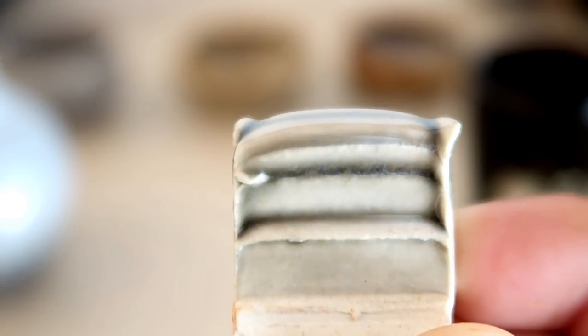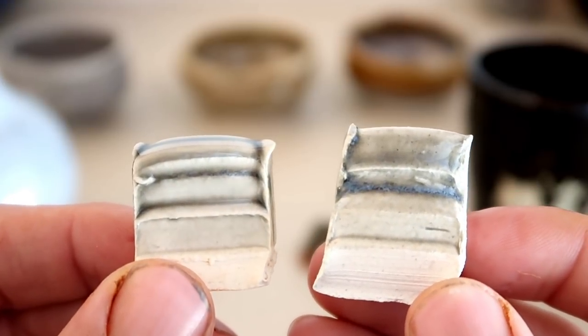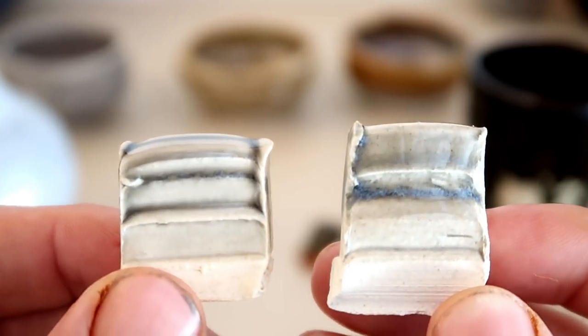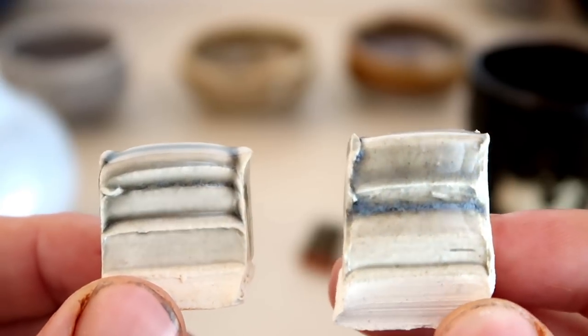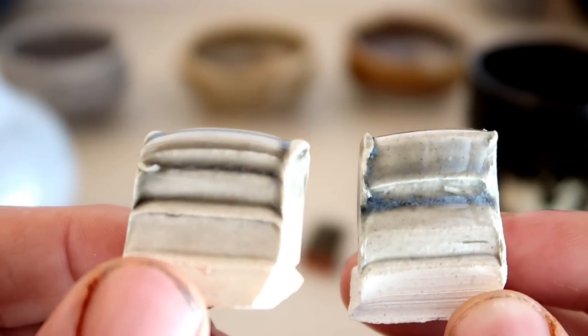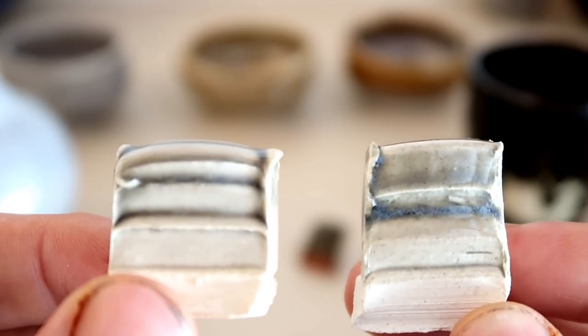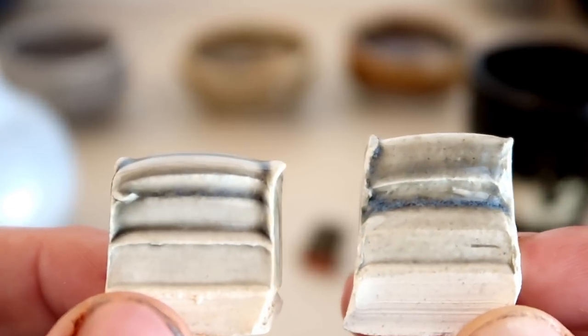This of course is on a porcelain clay body and this one looks a lot better than the B-Mix. I understand now why people mainly use this for porcelain. If we put the two side by side you can really see it — this one looks a lot more blue than this one. I wanted a gray, I didn't want a light blue. So on B-Mix it comes out this strange light blue, although it is a good glaze. I'll keep it in my rotation. This is what I was really looking for — that kind of deep, forest clearish gray.